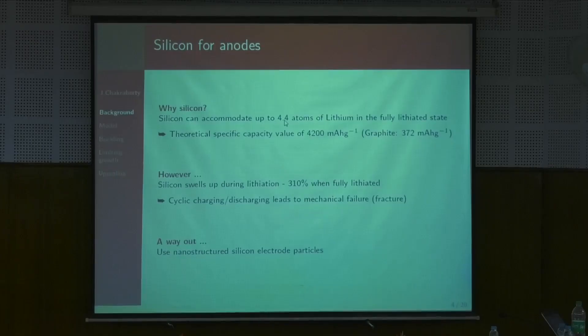Imagine you have tried to construct an anode using silicon inside the rigid confinements of a battery, and this silicon is swelling by more than 300 percent by volume — this thing will break apart. There is another subtle challenge: because the diffusivity of lithium in silicon is finite, the surface of the silicon particle will have high lithium concentration during charging, while the interior will have less. Because of this heterogeneity in concentration, different parts of a single silicon particle expand by different degrees, causing kinematic incompatibility, which leads to stresses that can cause fracture or other mechanical failure.